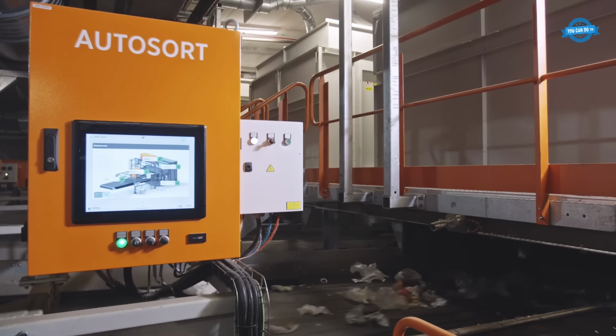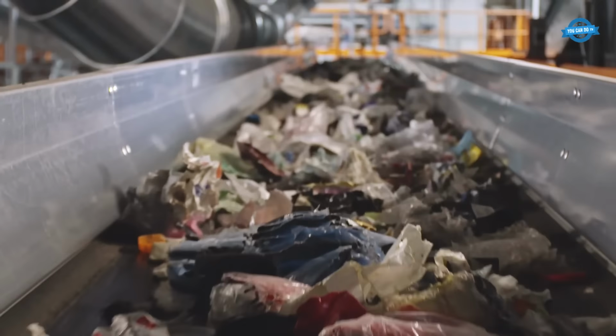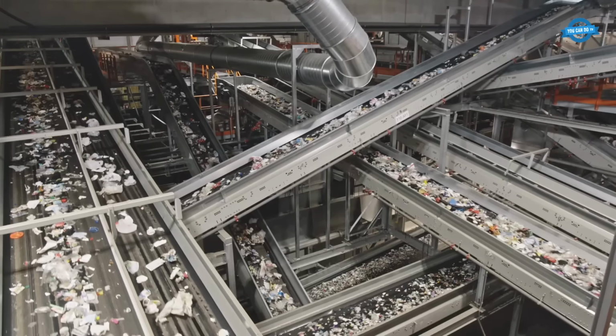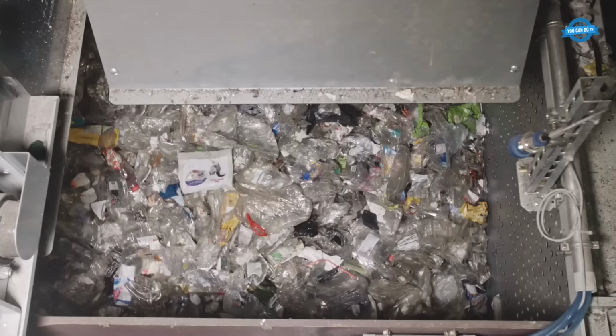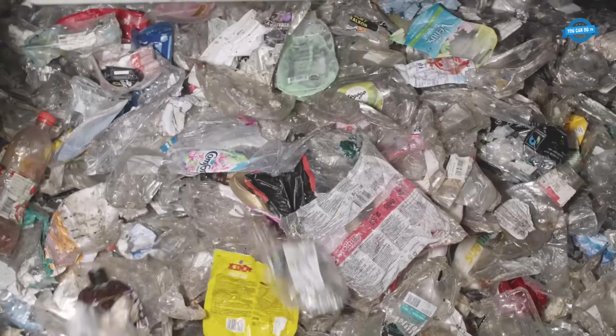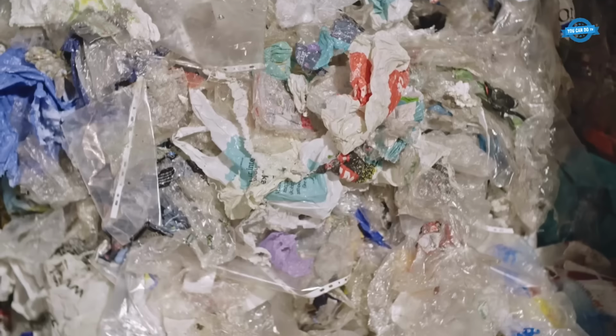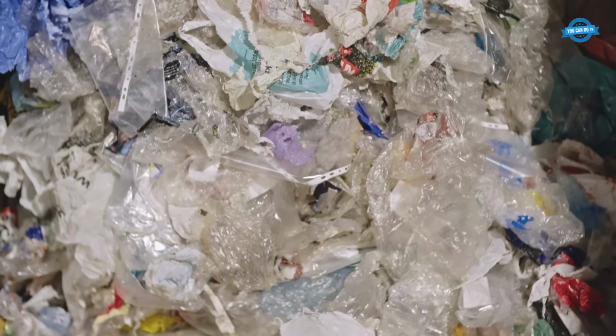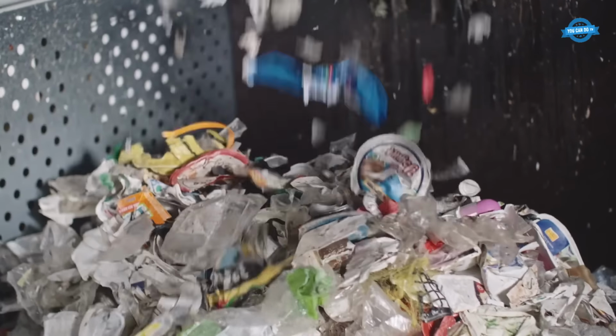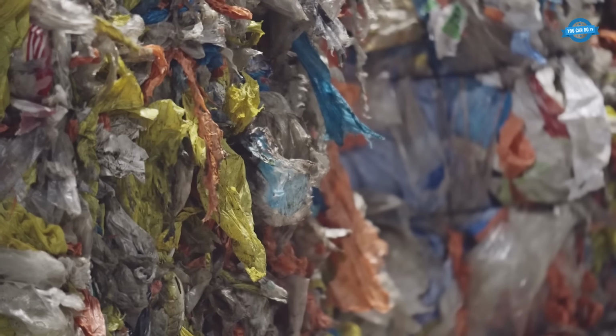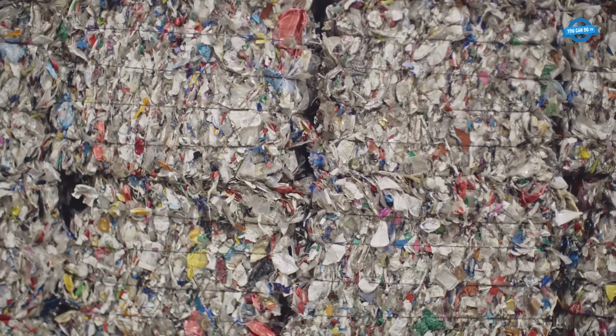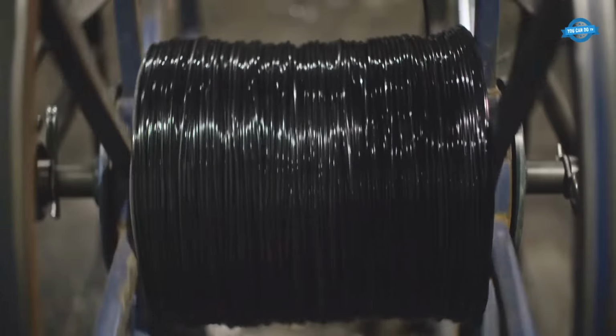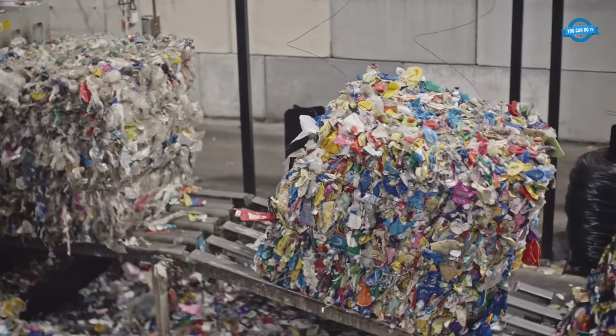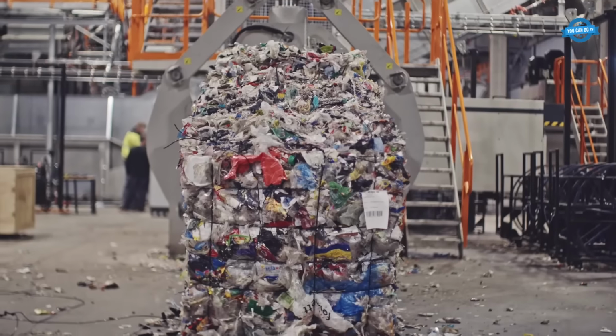The heart of the plant is optical sorting. 19 near-infrared sensors scan polymer signatures at high speed, identifying each material type and color in fractions of a second. The scanning process runs multiple times to maximize purity, producing 10 distinct polymer categories: PP, HDPE, PET, and others, each compacted into new bales for transfer to manufacturers who wash, grind, and pelletize them into recycled feedstock.